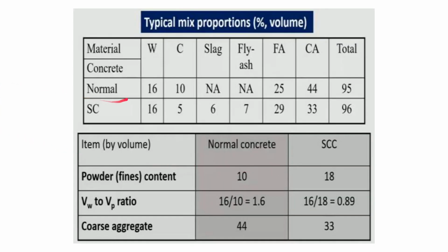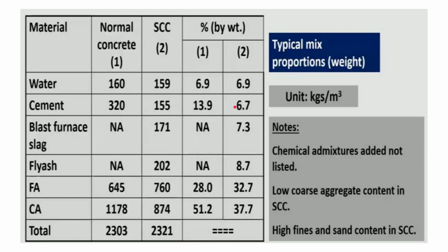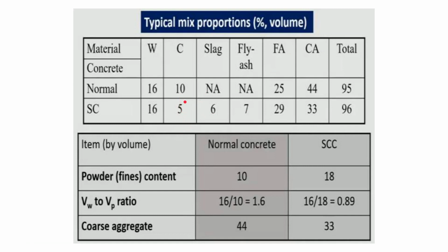So that is basically in percentages of weight. If we see in percentages of volume, there also we will find that water is almost the same, 16%. But the cement, as we saw here, in terms of weight it was less by 5%. Sorry, here also it is less by 5%. So the normal is around 10% volume, SCC around 5%, and with the addition of 6 and 7% of slag and fly ash, it comes to around 18%, which is 1.8 times more than the powder content of normal concrete.